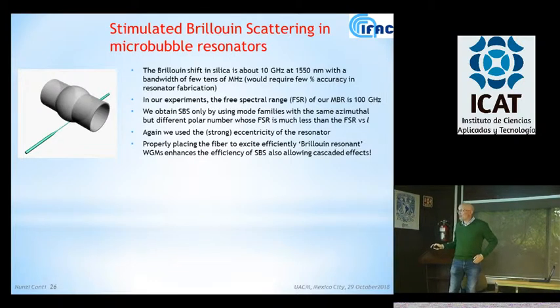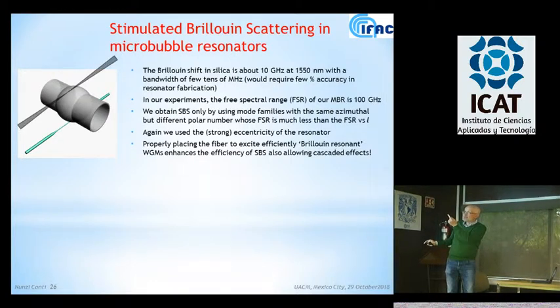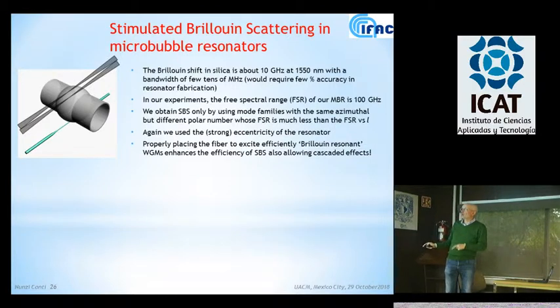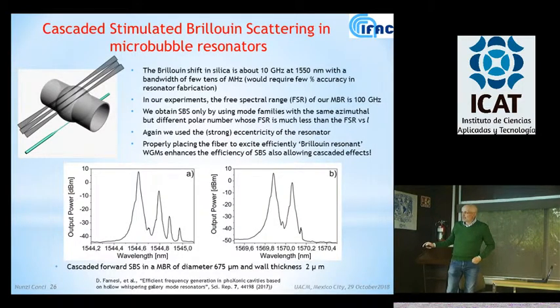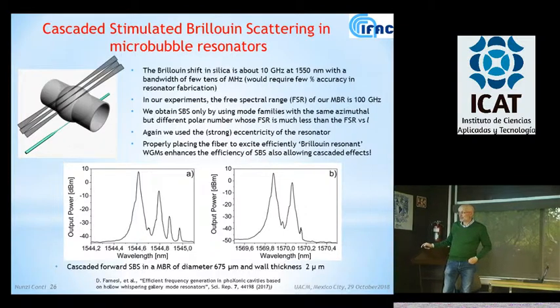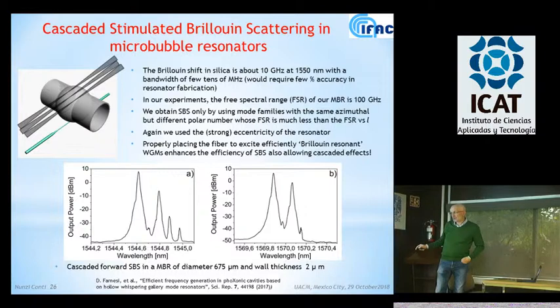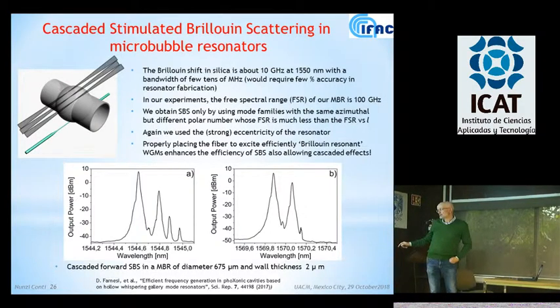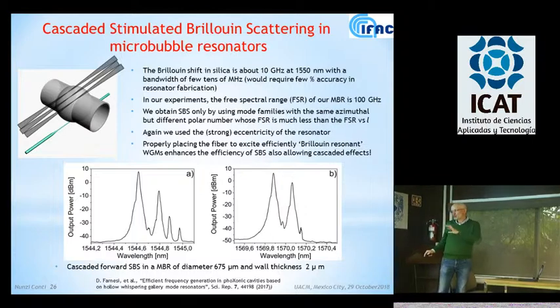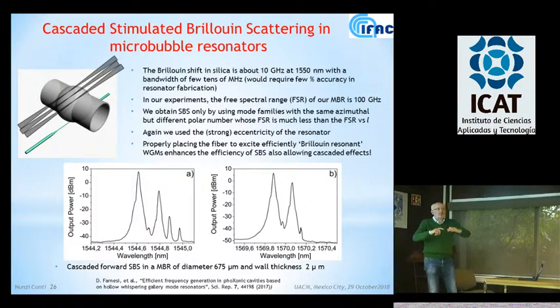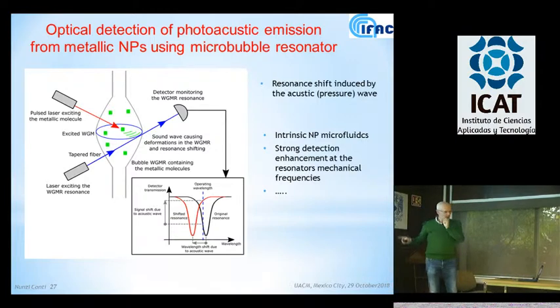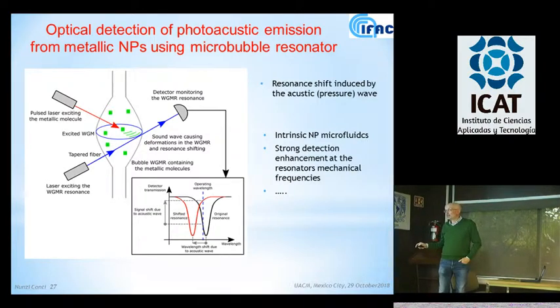And so basically by exciting those modes, which you can do by moving the fiber in the right position, we were able to obtain cascaded Brillouin scattering. Here you have different orders, and actually the even ones are more enhanced, sometimes the odd is much lower. But anyway, we could show that by exciting the proper mode with our taper, we could obtain this even in this structure, which has no possibility of being made with such precision. This is what we are working on. So it's the idea of the project.